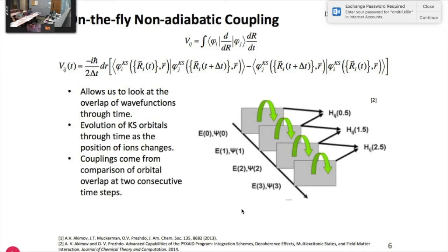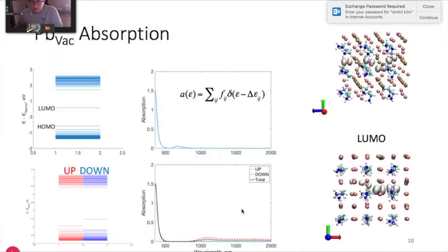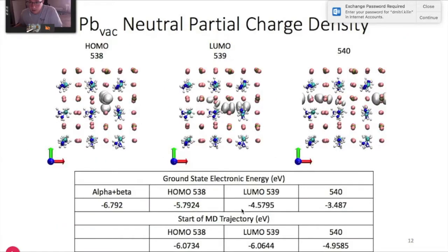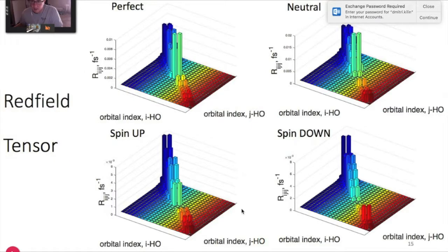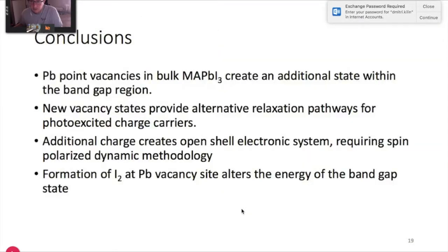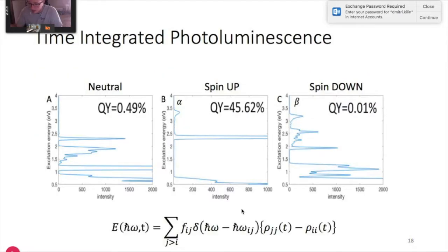I guess my question is about the quantum yield. So how did you calculate the quantum yield? Right. So for the quantum yield itself, it's the ratio of the radiative versus the sum of the radiative and non-radiative portions. So the radiative rates are calculated through the Einstein coefficient using the oscillator strengths of the ground state structure, and then the non-radiative rates come from our dynamics calculations, and so that's where the rates come from, and that's what I'm using for the quantum yield. Okay.